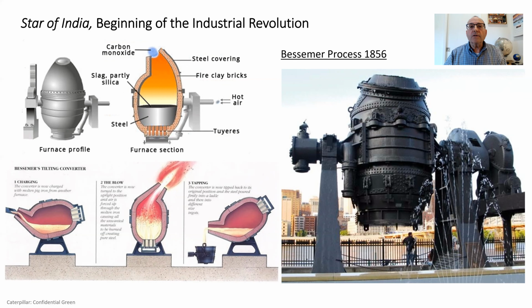And so the result of these two events occurring is that the price of these low carbon steels dropped significantly, like an order of magnitude. I've had a couple of ideas about how much it dropped. For an example, it went from about 70 to 7 English pounds per long ton, which is huge. And so what this did is this helped drive the industrial revolution. Now we could build locomotives, we could build cars, we could build bridges, big things. So this helped drive the industrial revolution.